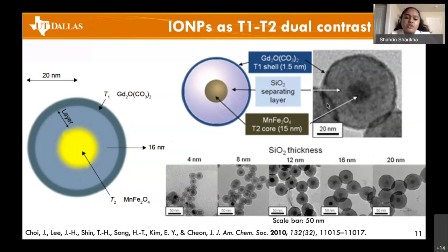So as you can see in this experiment, they didn't use iron oxide at all in the outer layer. And what this does is it allows water molecules to come into close contact with the paramagnetic centers on the surface of the particle, but also be affected by the superparamagnetic activities of the inner sphere. And so as you can see here, they were able to obtain monodisperse nanoparticles that later on, when they use it in vitro and in vivo, they observe these effects coming into play.